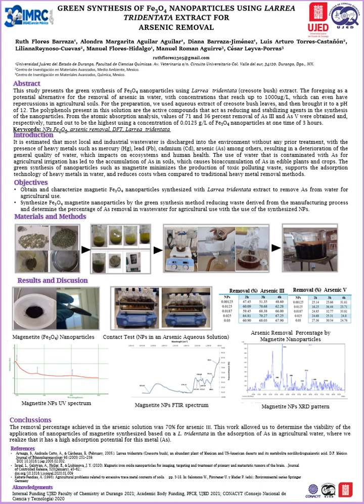The sample of creosote bush was first ground with the help of a conventional blender until a particle size that passes through the number 24 mesh was obtained. For the preparation of the extract, we used a plant material to solvent ratio of 1:5 in weight volume with hexane as our solvent in order to carry out the washings and remove the excess fatty acids, mostly resin, present in the plant's biomass. We let it rest for about 5 minutes until the resin present at the top formed a visible layer and then decanted it.